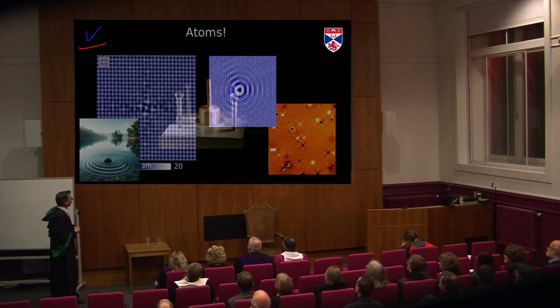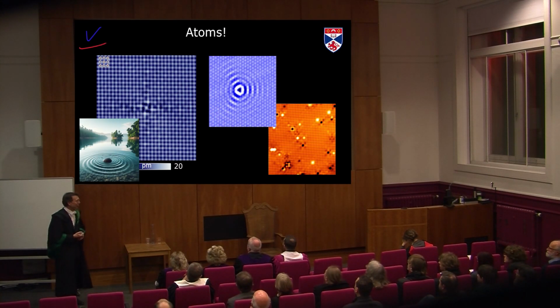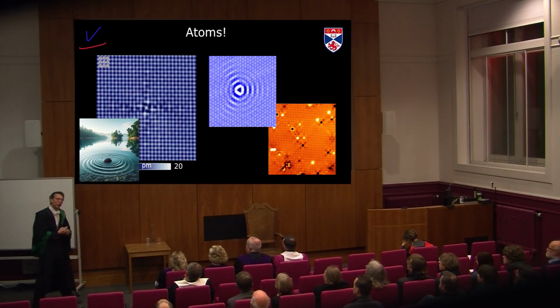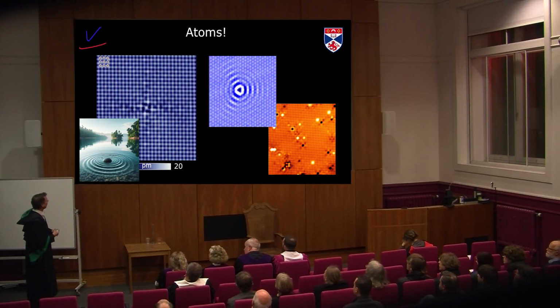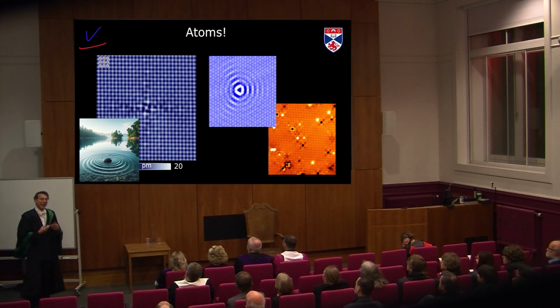Okay, so how do these images look like? So this is the kind of image which then lets our hearts beat a bit faster. When we see these nice atomic resolution images, that's kind of great to be able to see these atoms and to see them so sharp. They are not always immediately so sharp, but with a bit of work, that's the kind of images one gets. So here, this image here, this is an image of the crystal structure. Each of these white points here is one atom in the material. You see them on the crystal lattice.